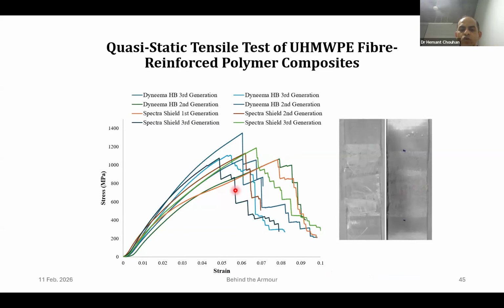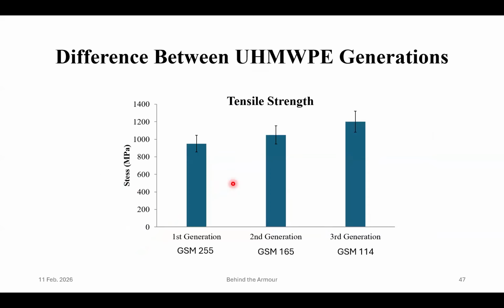what I call generation 1, 2 and 3. In the next slide, I'll show you what is 1, 2 and 3. So Spectra is by Honeywell and Dyneema is the other company. These are the stress strain curves of these materials and you can see the gauge section of these materials. Typically, the strengths are somewhere between 800 to 1400 megapascal as per my testing. And we found that as the generations grow, the GSM, that is gram per square meter, a term you generally come across with respect to paper, is going down and strengths are going up. That is the beauty of UHMWP and how the tenacity is helping us. In future we are expecting a fourth generation, and the strengths will go even higher and the GSM or the weight per layer will go further down.